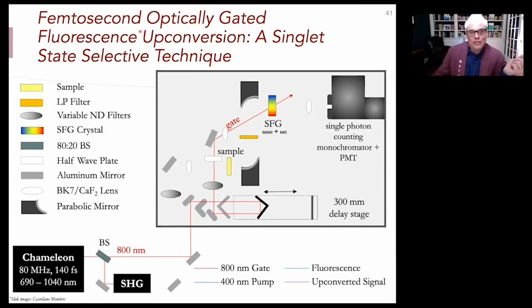For this particular case, we have to use fluorescence upconversion, but not photochemical upconversion. This is femtosecond optically gated fluorescence upconversion. This is how you can get lifetimes of fluorescent excited states on ultra-fast time scales. We have a Ti sapphire laser oscillator, and we use the 800 nanometer beam as what's called the gating beam, which enters into a sum frequency generating crystal. And then we can delay the time that the gate pulse arrives with a delay stage. That's how we get the timing for the experiment.